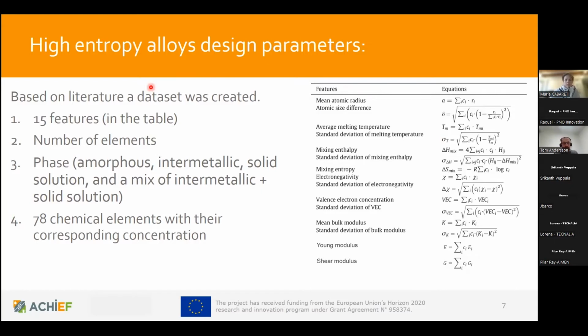train the neural network. So basically these 15 features, the number of elements, so usually more than 5 elements are needed so that we can call this alloy a high entropy alloy. Mainly more than 4 or 5, and usually those concentrations should be quite close to equiatomic, so meaning that there is not one element that is constituting the majority of the whole alloy. And then the third parameter was this kind of phase, so whether the material is amorphous, intermetallic, solid solution, or some mixture of these intermetallic and solid solutions. And finally, we have decided to use these 78 different chemical elements for this data set.